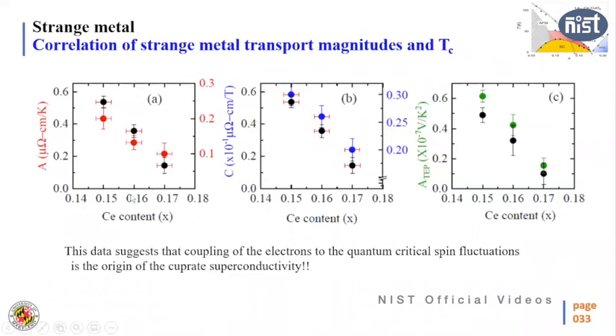It scales with all these constant values. What it means is that since Tc is decreasing, this A value is decreasing, or the C or ATEP value is decreasing. Now, whatever be the origin of this linear in T resistivity or linear magnetoresistance or logarithmic behavior of this thermopower, it is connected to this Tc, the superconducting temperature of this material.